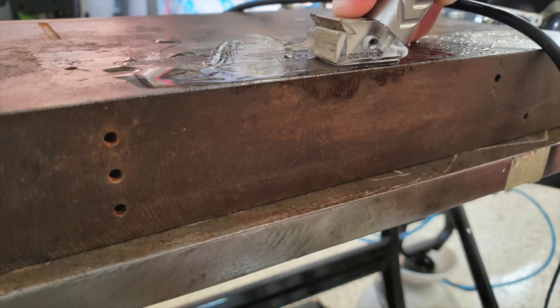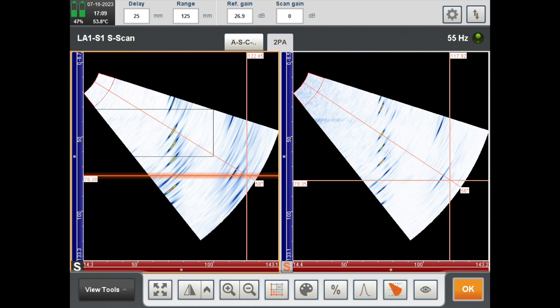The cost of using higher frequency is just gain. For example, on a 1.5-inch ASME block the 5 MHz probe is at 27 dB, whereas the 10 MHz probe requires 43 dB to bring the indication to the same level. Whether that affects you in the field depends on the material and thicknesses you're dealing with. But in my day-to-day, I just use high frequency whenever I can get away with it — I get better resolution and better characterization.